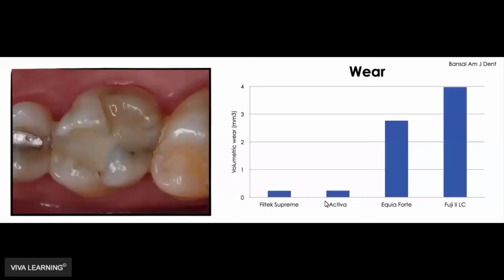This is data from our lab. So as far as wear, when we tested and published some data on wear, here's the wear of composite, much lower than the wear of glass ionomer materials. It's like 10 times less. It's way less than the wear of glass ionomer and resin modified glass ionomer material. And you can see Activa when we tested it, mechanically it behaves basically like a composite.